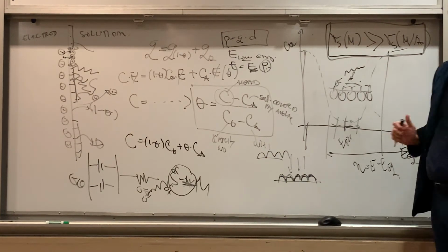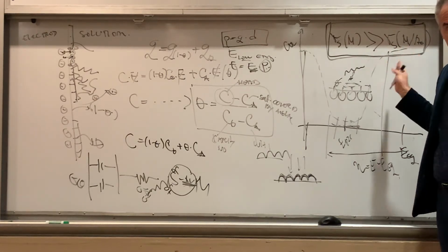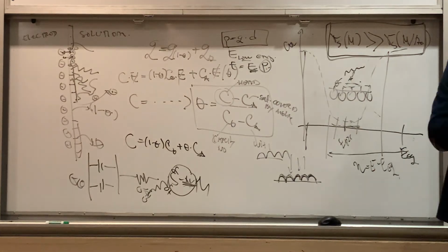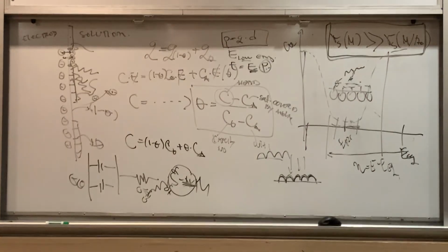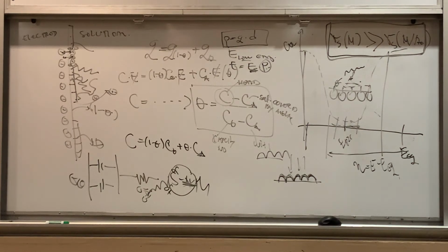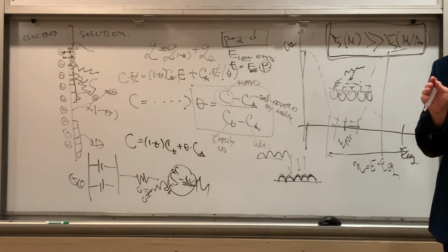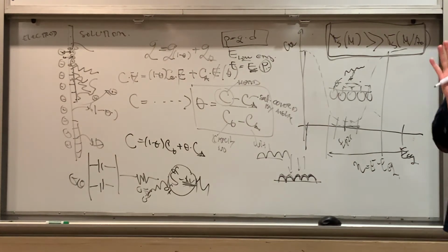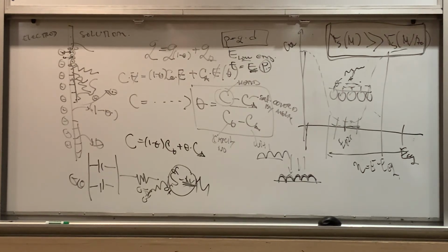Okay, I'm going to stop here, but this is very, very important for you guys to appreciate. Everything starts from here. When the organic phase is adsorbed on the surface, it changes the thermodynamics on the surface. So it's not anymore the surface energy of the metal, it's the surface energy of the metal covered with organic phase. Totally different concept, totally different number. What that really means, nucleation is not going to be the same. There are some other processes we're going to discuss that are not going to be the same.